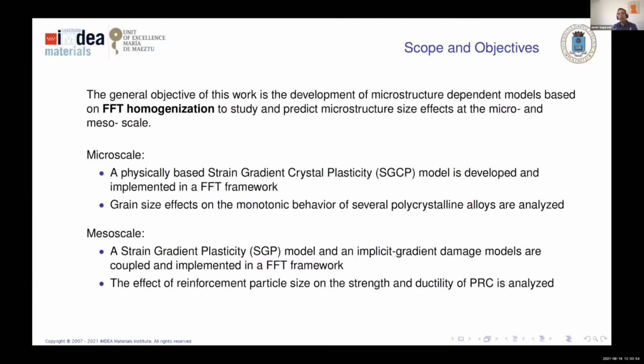In this case, we're speaking of another type of size effect. We're studying material size effect, and in this case the size effect comes from the relation between some characteristic length of the microstructure, not of the specimen, for example grain size, particle size, distance between particles, things like that, with some intrinsic length scale of the material.